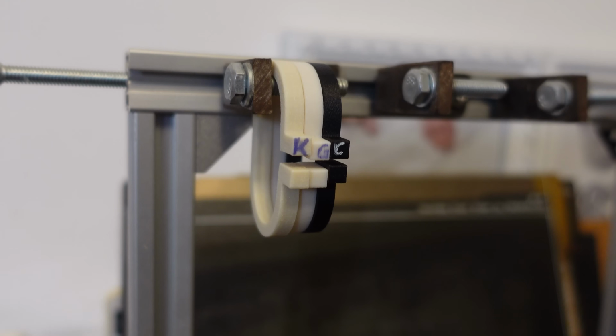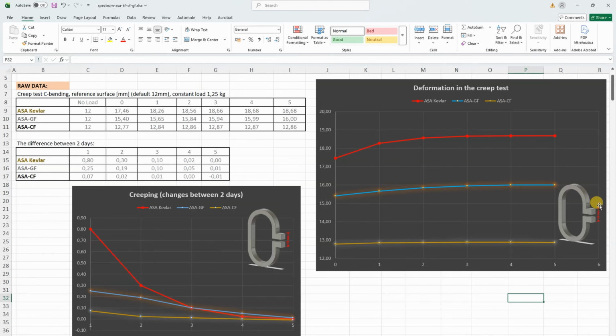Very small permanent deformation, but still the biggest one is on the Kevlar. On this graph we can see the distance between two reference surfaces, and we can see the biggest deformation on the Kevlar version and by far the smallest on the carbon fiber version. But the creeping is the difference between 2 days, and that's presented on the second graph, and we can see quite big initial creeping on the Kevlar version and by far the smallest on the carbon fiber version. Even on day 1 it is very minimal.